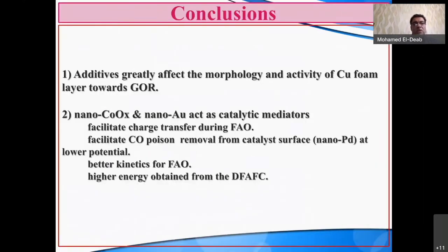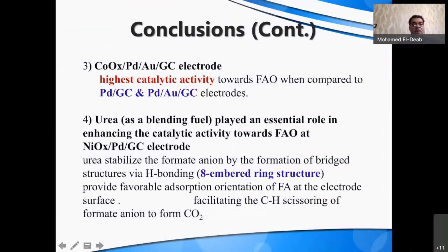Let me go to the conclusions directly. So we can say that additives greatly affect the morphology and activity of copper foam layers towards glycerol oxidation. Another conclusion: the nano cobalt oxide and the nano gold act as catalytic mediators, facilitating formic acid oxidation and also facilitating carbon monoxide poisoning removal from the nano palladium layer. And most importantly, number 4 here, urea as a blending fuel played an essential role in enhancing catalytic activity towards formic acid oxidation by stabilizing the formate anion, forming an 8-membered ring, supported by the DFT calculations, which facilitates the CH scissoring of formate anion to carbon dioxide.